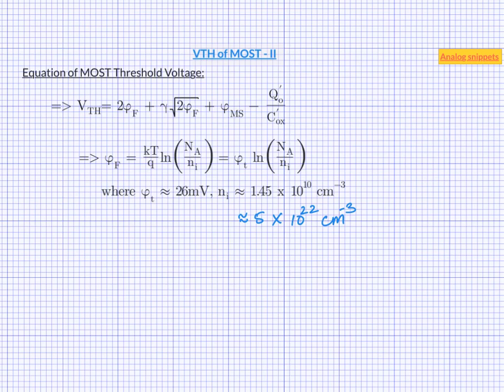Now free electron hole pairs are what carry a current in semiconductor. There is no wonder that pure silicon is almost an insulator. Let us consider the doping concentration N a. Even in a lightly doped silicon, N a is around 10 to the power 16 per cubic centimeter. This is almost 6 order of magnitude higher than N i.